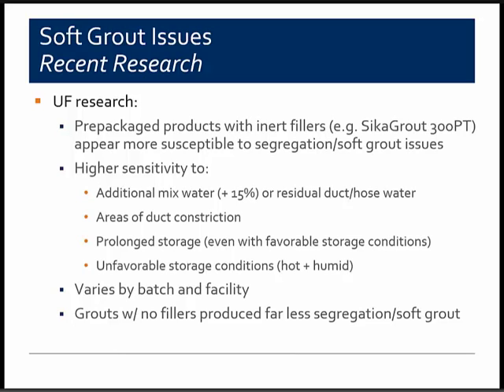Now, all of the tested grouts that the University of Florida looked at were new. In other words, none of them were the chloride-contaminated grouts produced in Marion, Ohio from 2003 to 2010 that we've previously discussed. And the results indicated that the susceptibility of the prepackaged grout products that were evaluated really varied by batch and facility, despite what I would assume is a similar product formulation within each batch and facility. It seemed to be much more random.